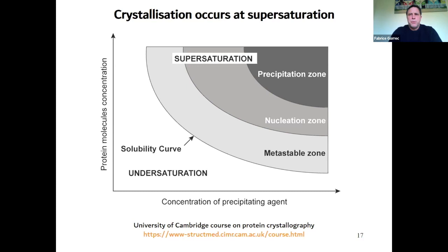So there are a lot of other parameters to consider. This is just to have a visual, something to view the process of getting more saturated. But for example, you have oligomers. These oligomeric states may vary according to the saturation level. There's a lot of other parameters in experiments, such as the surface tension, which may affect the stability of the sample, et cetera, et cetera. You have also samples that crash first, precipitate first, but then revert and crystallize. So, it's usually lots more complicated than this.